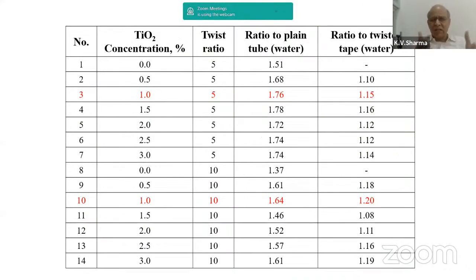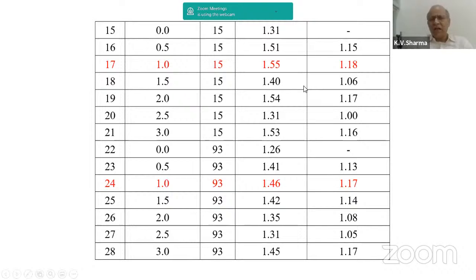Doing a similar analysis, just as we have done for a plain tube, we can go for a twisted tape. We find that with the twisted tape, for TiO2 at 1% concentration, with the twist ratio of 5, the enhancement is 76%. However, for the same concentration, when the twist ratio is increased from 5 to 10, the enhancement has come down to 64%. Like that for 15 and 93. As you can see, the red numbers are coming down because it is becoming very close to that of a plain tube.